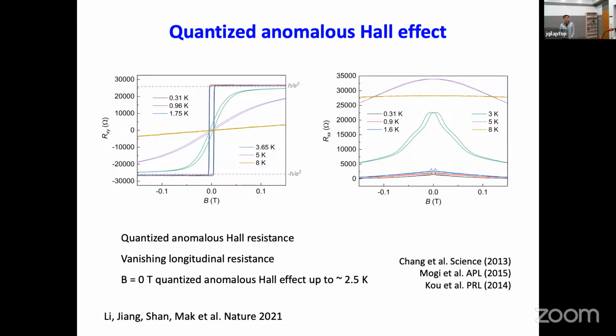at low temperature. These are the typical signatures of a Chern insulator, with a vanishing RXX and nearly quantized RXY near zero magnetic field. And you can also see a nice hysteresis loop with the magnetic field that shows really that ferromagnetism is developed, and the time reversal symmetry is spontaneously broken.